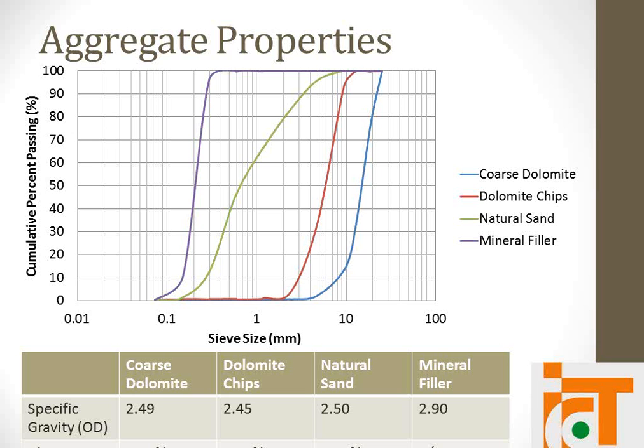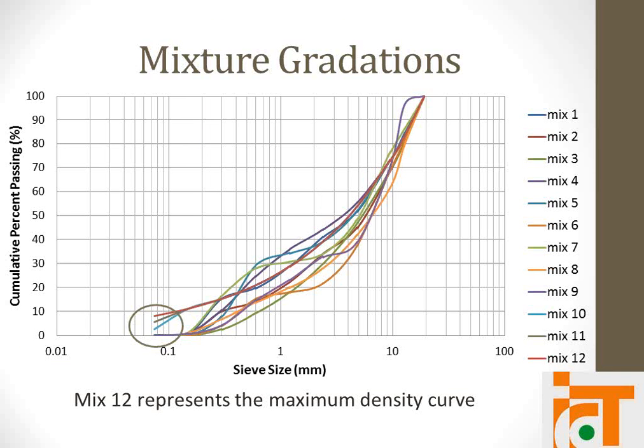Just some of the aggregate properties. We used 4 aggregates in this study: coarse dolomite that we have in the lab, dolomite chips, a natural sand, and some mineral filler for the higher fines mixes. So we did 9 mixes that had low fines, and 3 mixes with increasing fines contents, to test the effect of the gradation for the first 9 mixes, and for the last 3 to see how increasing fines contents affects the RCC. And this red one here is the max density curve going all the way up.